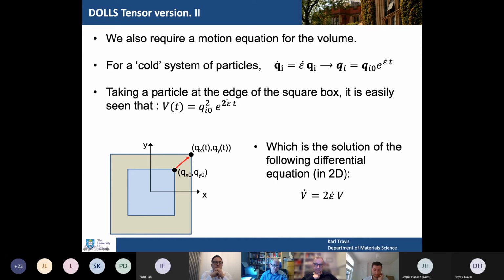So if we imagine taking a particle, if we come down to the left-hand corner here, we've got a simulation box. This light blue square is our original box at time 0. Let's pick a particle right on the edge, the top right corner of the box, with coordinates q x0, q y0. Let's expand the box to this bigger beige coloured box. Then the particle moves to this new position, and given that you know how the coordinates change with time, you can work out how the volume scales, and it goes like e to the 2 epsilon dot t. And therefore, you can recognise that that's the solution of the following differential equation: V dot is 2 epsilon dot V. And in 3D, it'd be 3 rather than 2.